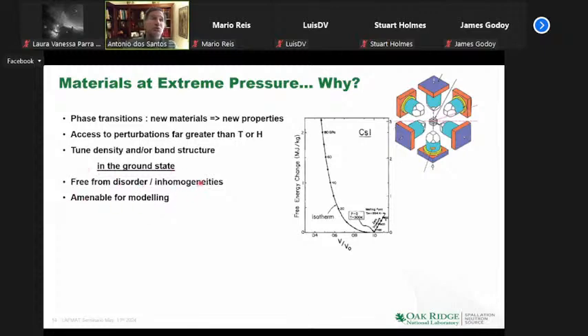This is true in the chemical sense. When you're doing manganites in the early days, people were doping everything, so you never really know if it's disorder or if there are inhomogeneities in the material. The reason why I say this is not really true is that sometimes when you apply pressure, you have to be very careful whether it's truly hydrostatic or not. Depending on where you are, you can start adding shear stresses, so you may change the material's properties with pressure. So this is not an absolute free lunch.